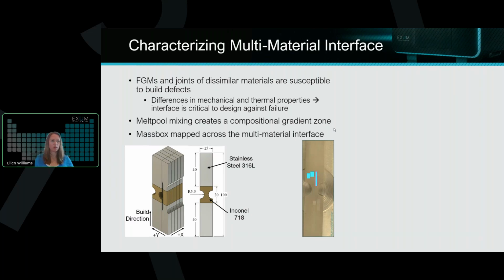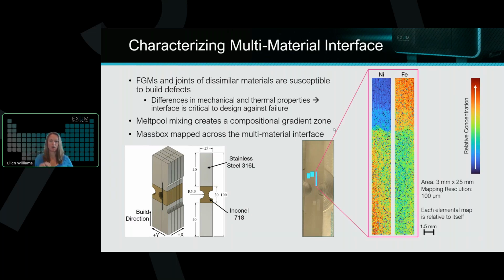So what a typical workflow looks like for us when we're looking for defects, looking for contaminants, is we'll do a relatively large scan with a relatively large spot size in order to find the area of interest. In this case, what we're looking for is exactly where that Inconel to stainless steel transition happened. So you can see we did this 25 millimeter long area across where we anticipated the material change to be, and then looked at the elemental maps here, again with a 100 micron resolution, so a relatively coarse resolution. We're looking at two maps side by side, again with the same color scale, where we see that relatively high concentration of iron compared to a low concentration of nickel, and then vice versa on the other side, we found that interface. We know that we see the nickel alloy on the bottom, and that has transitioned to the stainless steel on the top.